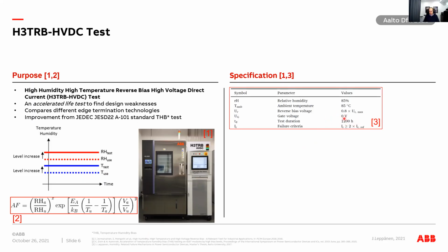Typical test durations are 1200 hours or 1000 hours. It depends entirely on who does this test, and it's not relevant typically, because the good components are really immune to these kinds of issues, and it's a sort of either the component fails or it doesn't fail, and of course sometimes you can see differences between different types of chips, but typically the result that is wanted from this test is that the components should pass this kind of a test.